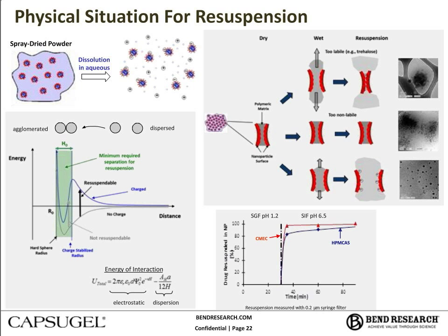On the other hand, large water-soluble polymers are sometimes prone to forming gels before they can disperse. And so that can not be very efficient for redispersing these nanoparticles either. The example there is shown in the middle row of the resuspension schematic in the right of this slide, where we've used a high molecular weight polymer. And the TEM images show the gelled particles there as well.